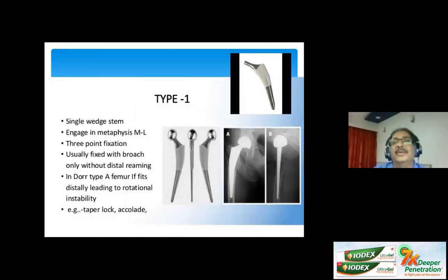This is type 1, which is the proximally coated single wedge stem, which engages in the metaphysis. It has a 3-point fixation, and you have to be very careful that in certain femurs, it should not just have a distal fix with no proximal support. That is where it tends to be a problem. The Accolade, the Taper-Lock, Accolade Stryker, or the ML Taper by Zimmer are classic examples of this.